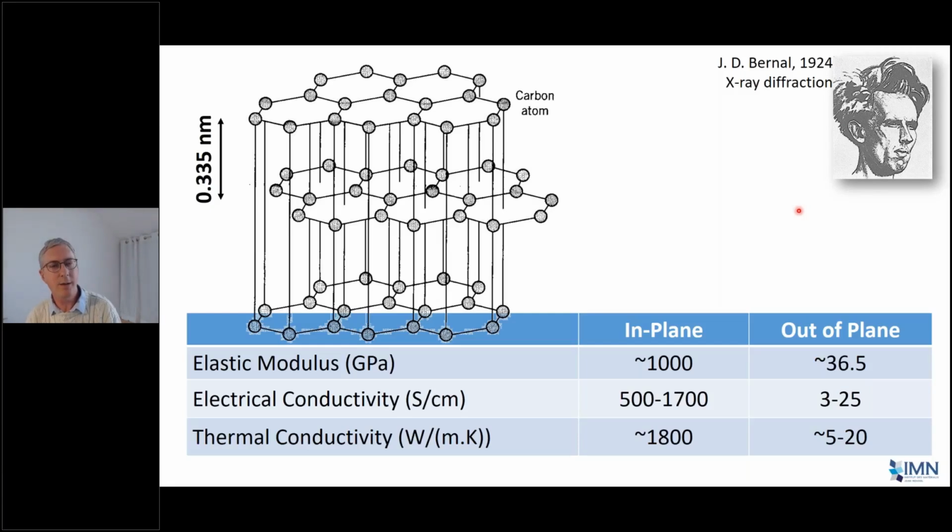And it's highly anisotropic, so the bonds between the carbon atoms in the layer are extremely strong. So you can see you've got an elastic modulus of a terapascal, that's extremely high. And in principle, if you could make an ideal sheet of graphene, a single layer of graphite, so you wouldn't be able to see it, you could balance a pencil on top of it, on this point, put an elephant on top of that, and it wouldn't break. I mean, that's a thought experiment. I don't think anybody's actually tried that.